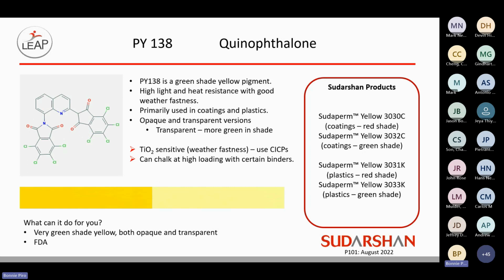Pigment Yellow 138 is a very green shade, as I mentioned earlier. It is the most green shade yellow pigment in the high performance categories. This one can be in opaque or transparent versions. The transparent will be more green in shade. It is TiO2 sensitive, so this is another area where CICPs might be a good option to get that color space with weather fastness. On the liquid coating side, the Pigment Yellow 138 can chalk at high loadings with certain types of binders, so some additional formulation care will be needed in that specific